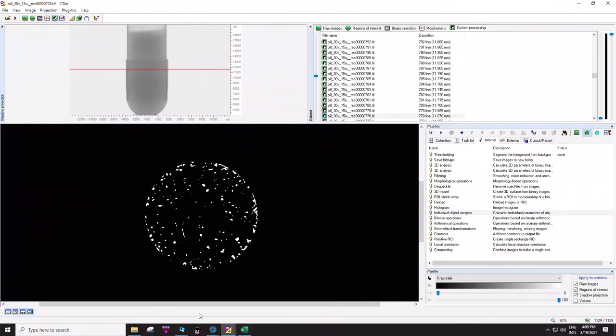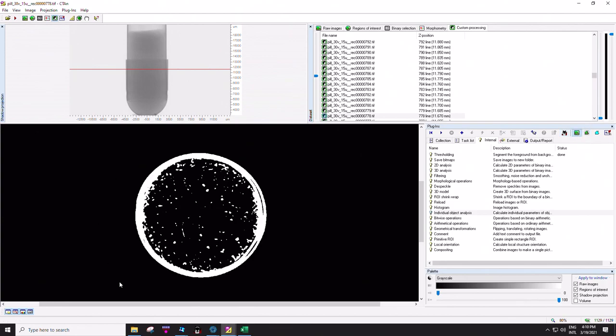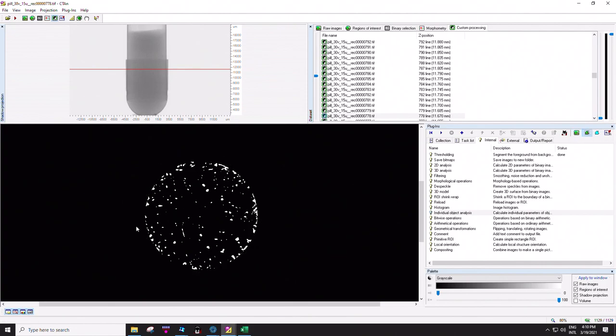I would actually go into a program called CTAn. Here's a cross section through your data, and I've highlighted all the high density material. Your capsule shell is not something you want to look at, so I can actually mask it out. Here you have just the active ingredients. Now I can run a program that will actually go through and identify each of these individual active ingredient particles, calculate their X, Y, Z, and size. Then I can get a particle size distribution and a distribution of how they fit inside — are they equally distributed? Things like that.